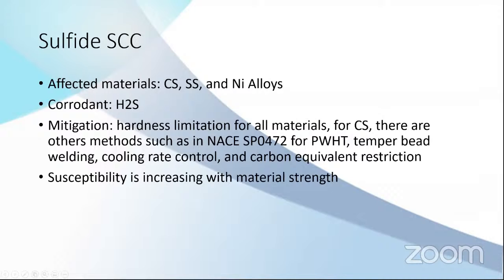So this is the general mechanism. The higher the strength, the more susceptible it is. But why is hardness used? Because it's the easiest method to measure the material strength. Strength and hardness are linear, so using hardness is somehow equal to using strength. Normally the limits are 22 Rockwell C or 248 Vickers. That's the rule of thumb.